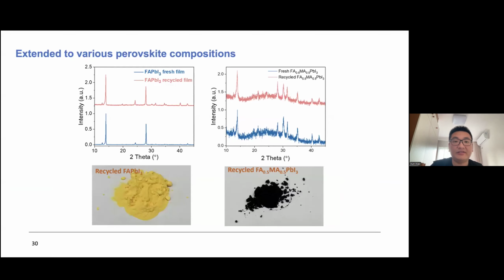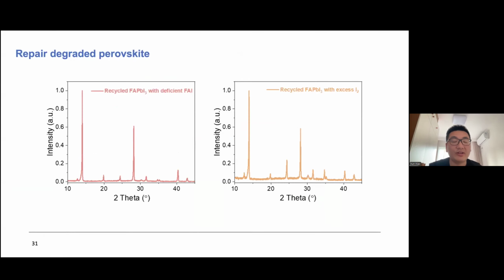We also extended this process or technique to different perovskite compositions. We found for FAPbI3, it's easy to recycle, and we also tried to recycle the FAPbI3 and MAPbI3 one-to-one mixture. It can also be used. And also we were trying to demo whether our technique can repair the degraded perovskite or not. So we recycled the FAPbI3 with deficient FAI inside, and it can still be good. The recycled film can still be a good crystallized perovskite film. And also we recycled the FAPbI3 with excess I2. It can still be a good perovskite film.